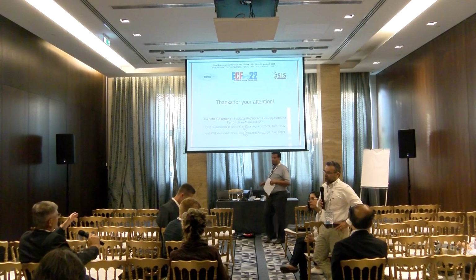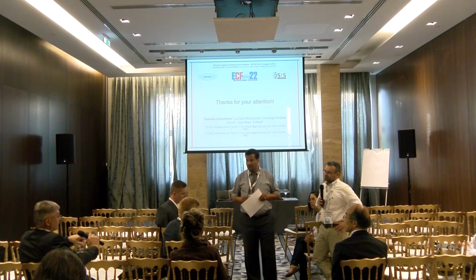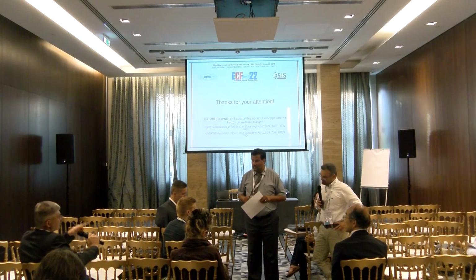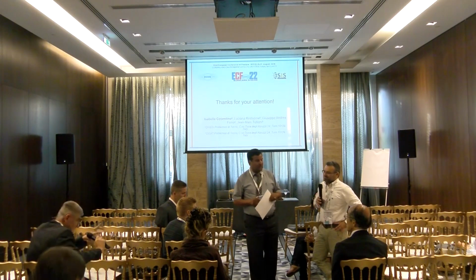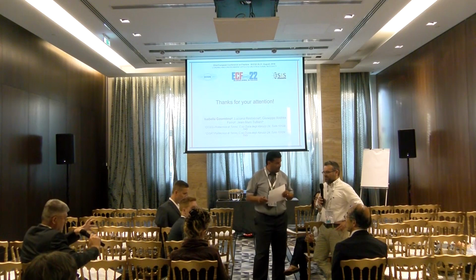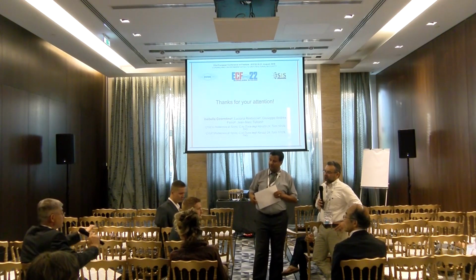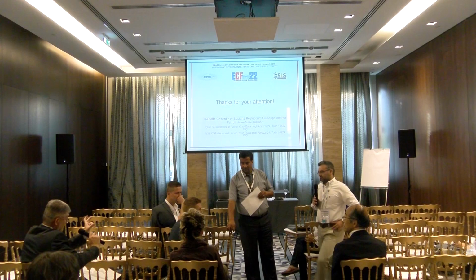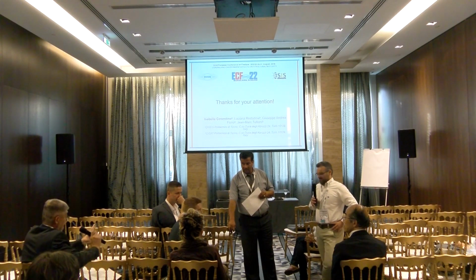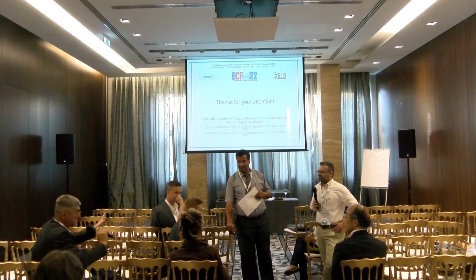When you have the results, you see that the cracking occurs sometimes even in the nugget zone, depending on how severe the corrosion test was. So basically, the critical place, as the thermomechanically affected zone or near the nugget zone, is now something else. So it's rather a question of what the gentleman said. We have here two things. One is chemical in nature. The second one is thermomechanical in nature. Depending on where the governing process goes, we have different outputs. That is probably the nightmare for everyone who is a designer in mechanical engineering. I'm a metallurgical engineer, so my knowledge and my ideas stop there. It's the other people who have the challenge.